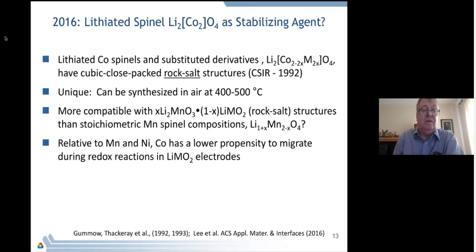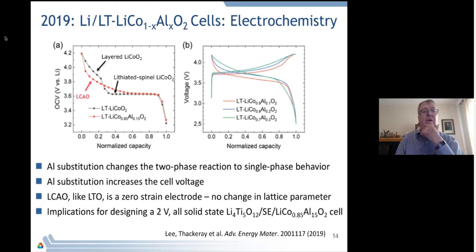Another advantage is that relative to manganese and nickel, cobalt has a low propensity to migrate during the redox reactions in these composite electrodes. What we have found fairly recently is that aluminium substitution in these lithiated cobalt spinels does some really wonderful things.